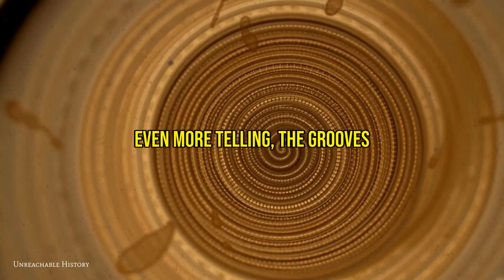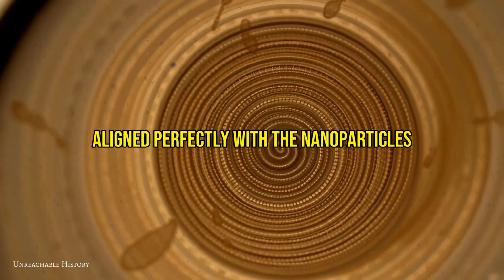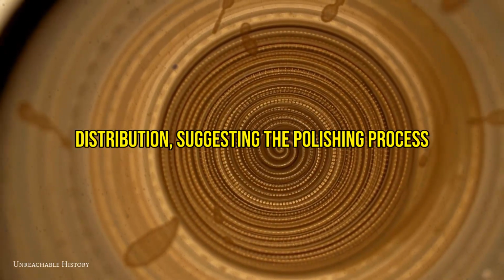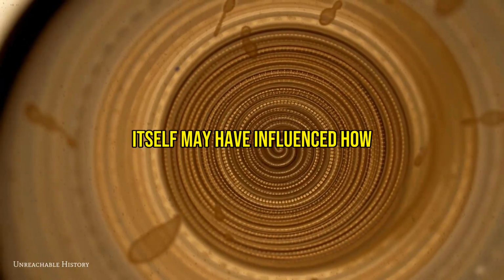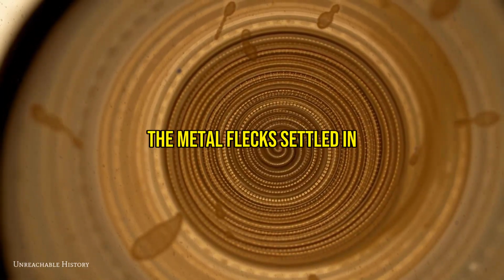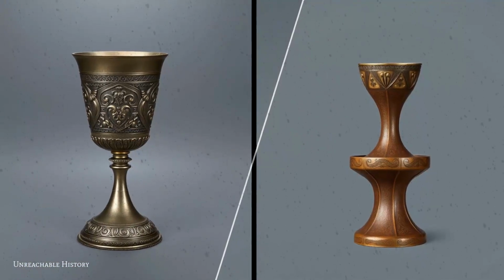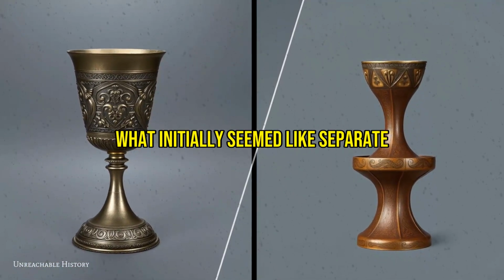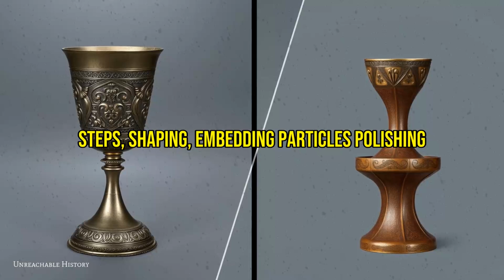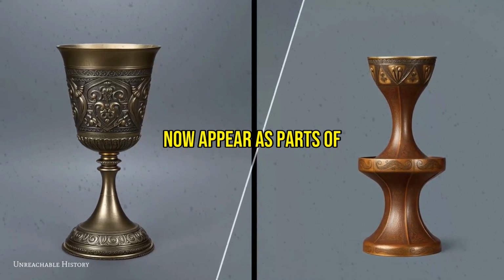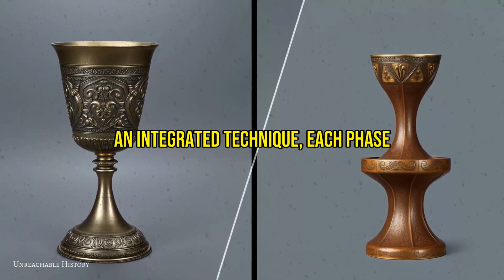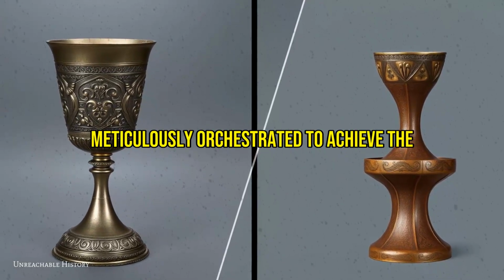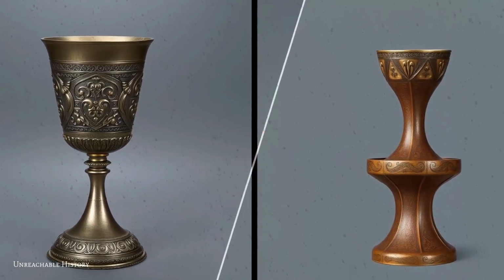Even more telling, the grooves align perfectly with the nanoparticles distribution, suggesting the polishing process itself may have influenced how the metal flecks settled in the glass. What initially seemed like separate steps, shaping, embedding particles, polishing, now appear as parts of an integrated technique, each phase meticulously orchestrated to achieve the final effect.